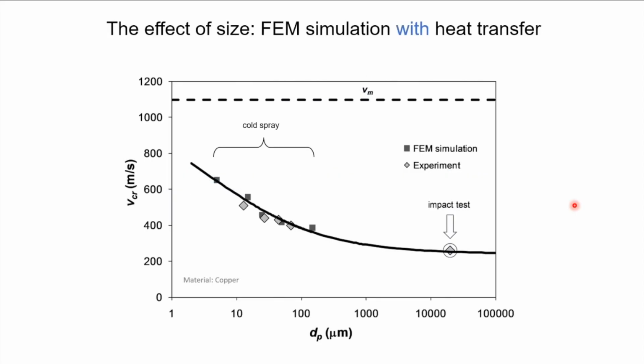Now, proceeding with the finite element simulation, we could then investigate the effect of various other parameters like the size of the particle. Doing some finite element simulation with heat transfer, we realized that the larger particles are more prone to bonding, so you can get them bonded to the substrate at a lower impact velocity, because the time of the extraction of the heat with respect to the size of the particles becomes more prominent. It's a bit of mathematical complexity here, but I think this has to do with the heat transfer equation and the wave propagation equation, and the way that they're formulated will give you that.